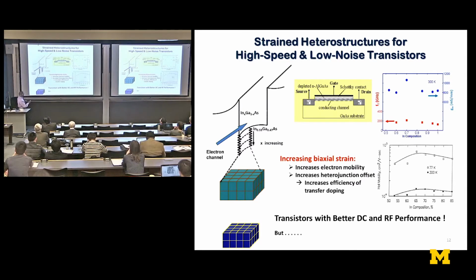And so these are some of the results, and we started adding more and more indium. So 53% is the lattice matched composition, and then we started adding 60, 70, 80%, and as much as we could. And these are some of the results of the mobility of these heterostructures at room temperature and low temperature, and then the actual, in the submicron devices, the measured cutoff frequencies and the transconductance or the gain. And you can see we were making very decent devices of transconductance over 1,000 millisiemens per millimeter and cutoff frequencies of about 200 gigahertz. This was state of the art at that time. But one thing we noticed at that time, that all these parameters were increasing, they peaked, and then they would go down. And we just didn't understand this.